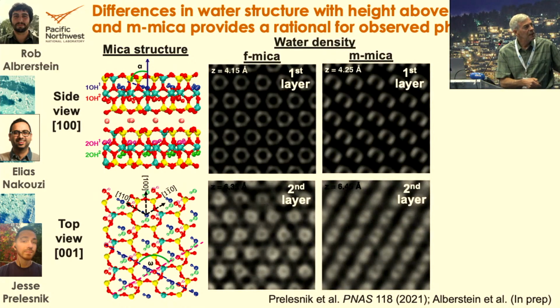So what the molecular dynamics shows us is that if we look at fluorophlogopite, I should say, so that's the F-mica. In fluorophlogopite, the OH is replaced by fluorine. So this directionality is completely removed. And now when you look at the water structure above the surface, even though these OH groups are down below the surface, what you see is on fluorophlogopite, you have a hexagonal pattern in the first water layer, and the waters point in all three directions. And the second layer is still hexagonal, and then you can't even see the structure by the time you get to the third layer. But on muscovite mica, even though you have a hexagonal pattern of water, it's unidirectional.